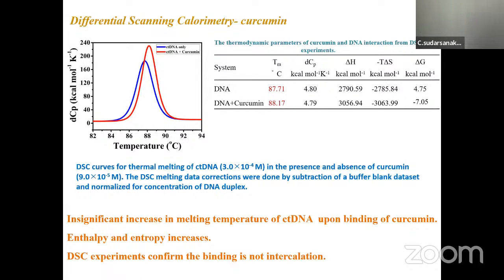So there won't be any major changes found. The melting temperature found is 87.71, and in the other case it is 88.17. By melting, what we understand is that 50% of the DNA separation takes place. The duplex DNA will split up into single strands, almost 50%. This is what the calculation says in differential scanning calorimetry. Since the temperature difference is not much, we can easily assume that this is a groove binder.